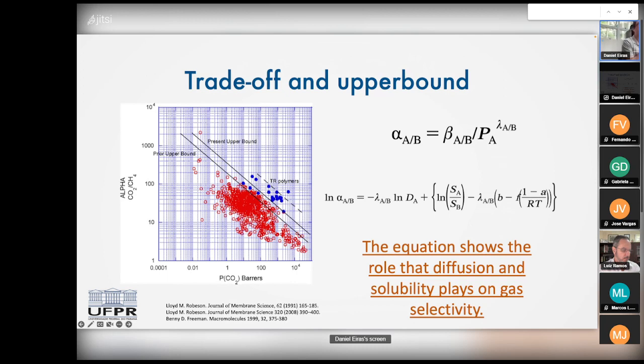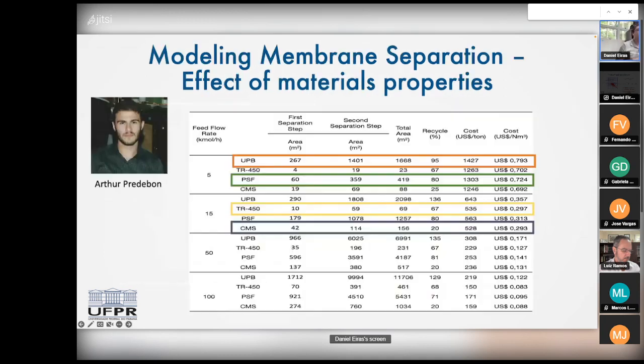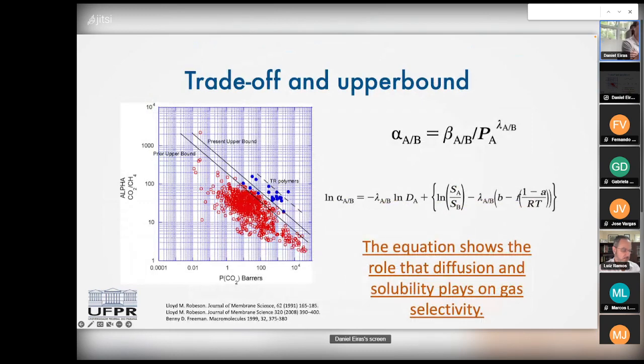This first equation can be modified to correlate the selectivity, the diffusion coefficient, and the solubility coefficient, DA and SA, SB. So what we can get from that equation is that if we increase the diffusion coefficient, we increase the permeability, and we reduce the selectivity. At the same time, we can increase the solubility selectivity, SA divided by SB, to increase the selectivity. So the two ways that we can improve the properties of polymer membranes is to modify the polymer so we change the diffusion coefficient, or we change the solubility selectivity. The problem we usually have is that when we increase one side, we end up decreasing the other side.